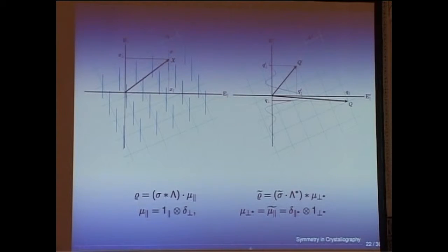Now if I want to make the Fourier, don't forget I'm interested in the Fourier, I just put a tilde everywhere. Each time there is a simple product, it becomes a convolution product. So this is the Fourier transform of the double Heaviside function, so it's a cardinal sine, this stuff. This is very important: it means that on each point of the reciprocal lattice in two dimensions, you take a sampling of this value. By taking just that, you see that you have points. That means that whatever I do after, what I will see on my diffraction pattern are bright peaks, not diffuse scattering. It's not diffuse. There are points.